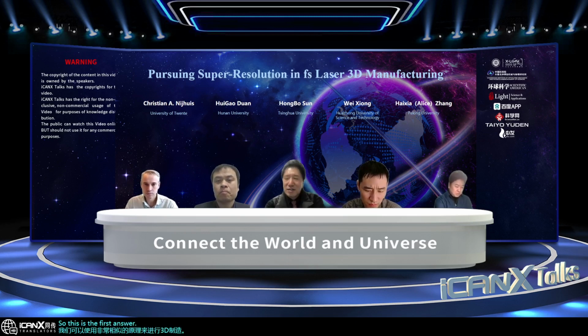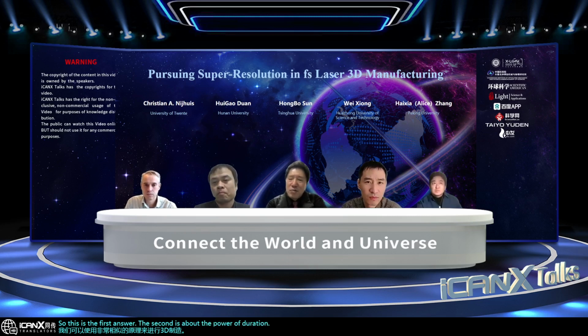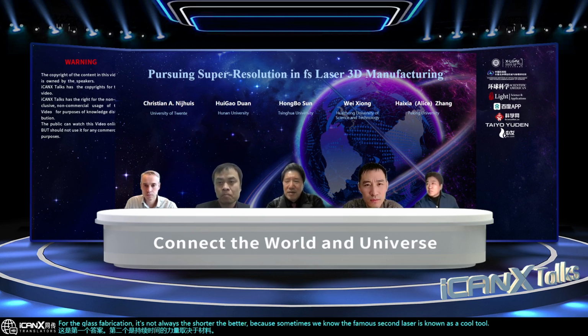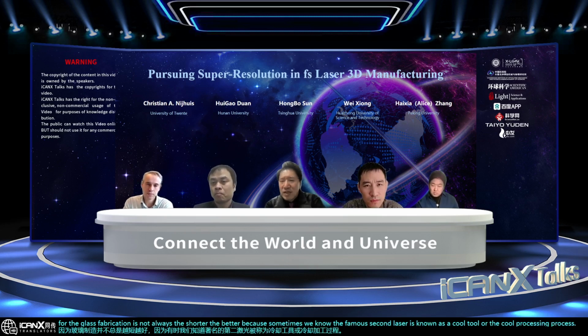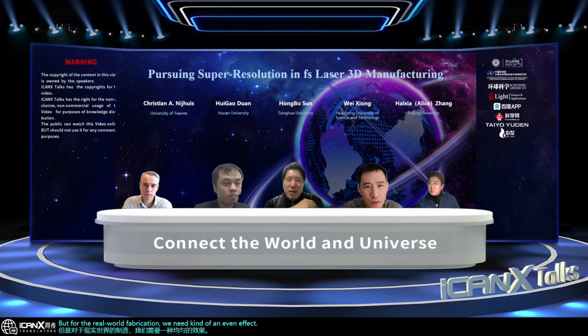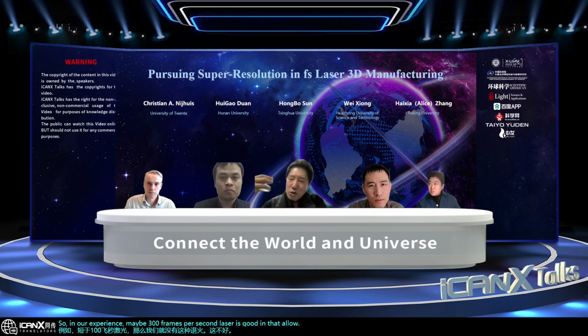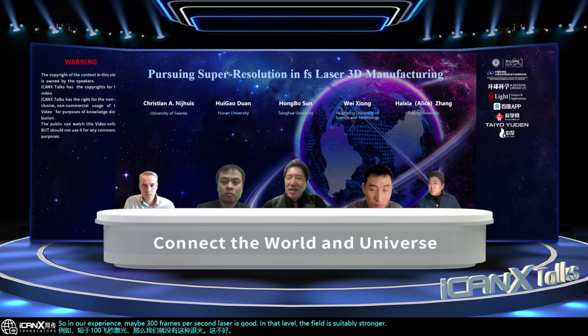The second is about laser pulse duration. It depends on materials. For example, for the glass fabrication, it's not always the shorter the better, because sometimes we know the femtosecond laser is known as a cool tool or the cool processing process. But for the waveguide fabrication, we need kind of annealing effect. So if the laser pulse duration is too short, for example, shorter than 100 femtosecond, then we have no annealing. It's not good. So in our experience, maybe 300 femtosecond is good. In that level, the field is suitably stronger, and annealing can be well done to some degree. So this is for glass.